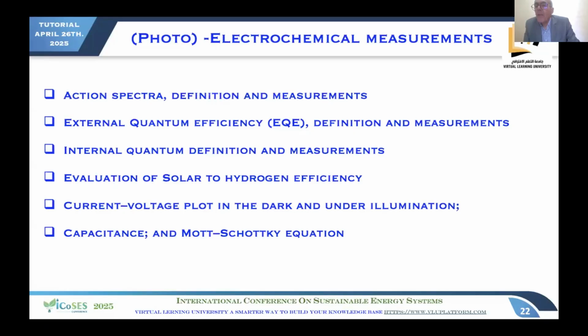Another question from Ismail Abbasi at 4.1. How does the electrochemical reaction temperature affect the cell yields? Yes, the temperature, and here you can go back to the density of state in the electrolyte. You have to control the temperature, because every movement of the electron makes an Ohmic effect, which can make heat, and this T delta S in the free enthalpy makes heat, and this heat can make your cell not perform correctly. So you have to control the heat.